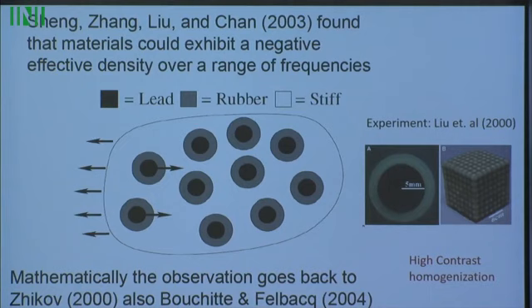So there were actually experiments in 2000 by the group of Ping Sheng exhibiting negative effective density, and in 2003 they actually understood what was happening. But basically, if you've got a material like this, this is a rigid body, this is rubber around here, these are lead balls. If you oscillate this back and forth, then above the resonant frequency, the lead will actually be going this direction, whereas the surrounding matrix here will have a velocity going in that direction. So the relation between the physical velocity, which is all you measure from the outside, and the momentum of the lead, which is the heaviest component, they're in opposite directions. So you've basically got a negative effective density in these materials.